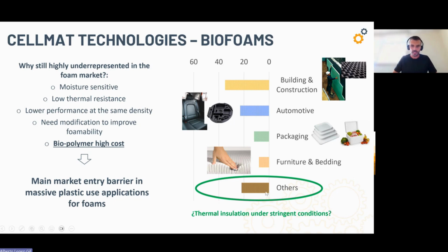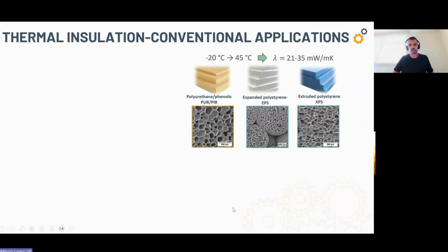But there are other applications for foams in which maybe the cost of the biopolymer is not such an important drawback. For instance, thermal insulation under very stringent conditions. And let me explain why. Here you see the main polymer foams that are used for thermal insulation under conventional conditions. When I say conventional conditions, I'm referring, for instance, to the temperature these foams need to withstand in real application conditions. For instance, these conventional foams are good at providing good thermal insulation, very low lambda values within this range, at temperatures within -20 up to 45 degrees. We can say these foams are able to cover a good thermal insulation in many different regions of the world.